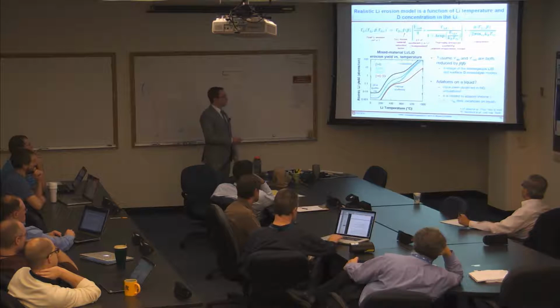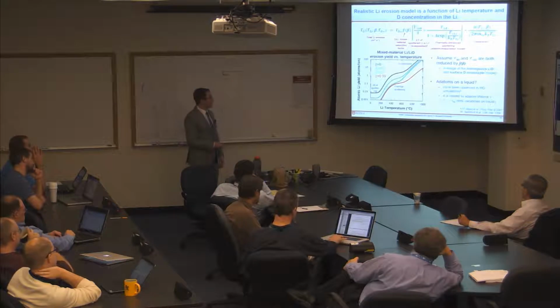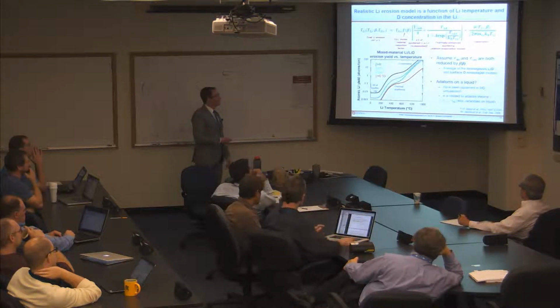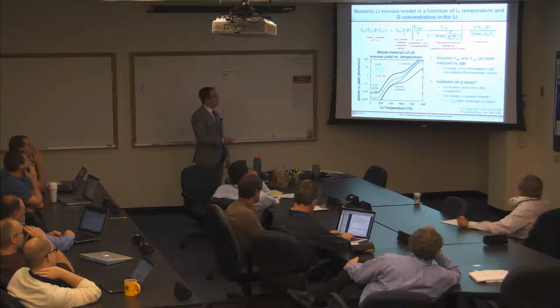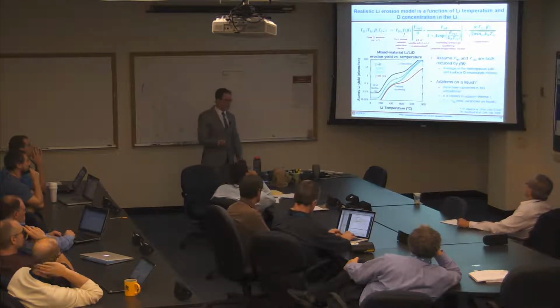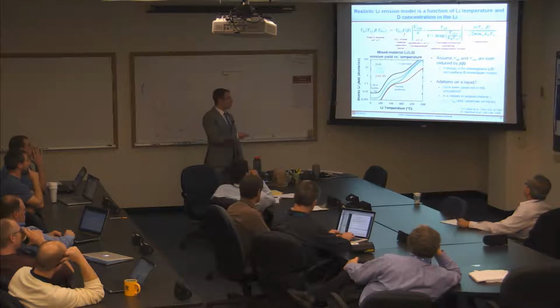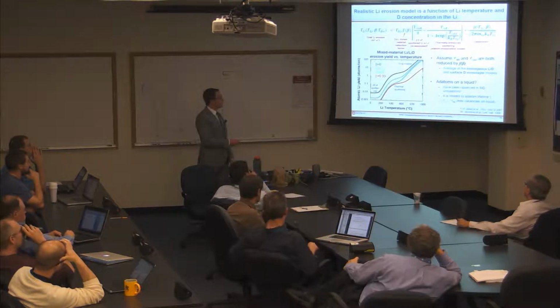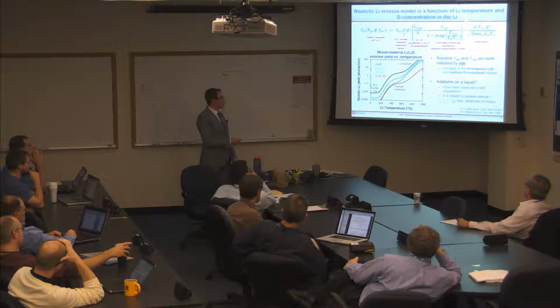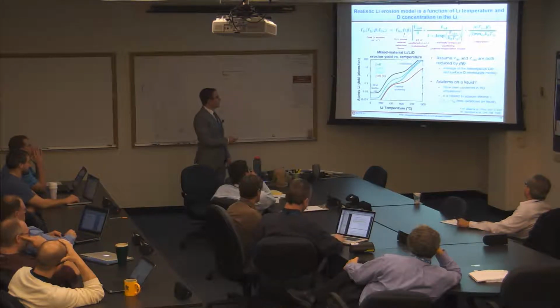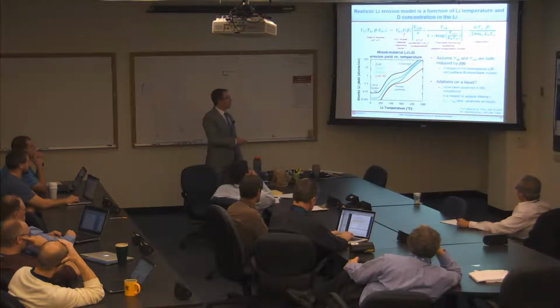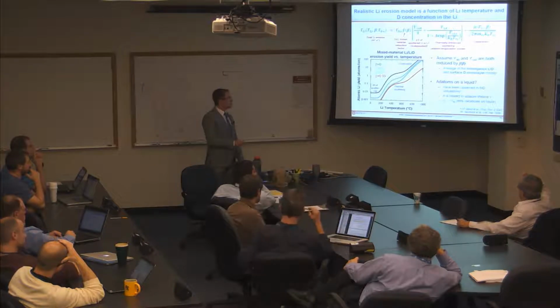And this term right here is the thermally enhanced sputtering due to the evaporation and sublimation of adatoms. This formulation comes from a paper by Russ Doerner on PISCES, and these coefficients Y, A, and E are all fit parameters that I fit to the data from PISCES that I showed you on the second slide of the introduction. So we're assuming that the so-called collisional sputtering yields and thermally enhanced sputtering yields are both reduced by the same factor F of beta, which is this mixed material reduction factor. And then you also have the evaporative term, which is reduced as a function of beta as well.